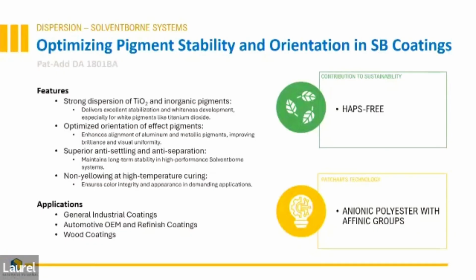Our solvents now evaporate much slower because we don't have 15% solids anymore, right? Those coatings don't exist anymore, the lacquers, the 12% to 15%. Now we use lower molecular weight materials that are, let's say, more fluid during the application process, don't evaporate, and now the film thickness is big enough that these flakes will actually rotate and move around and give us reverse flop.